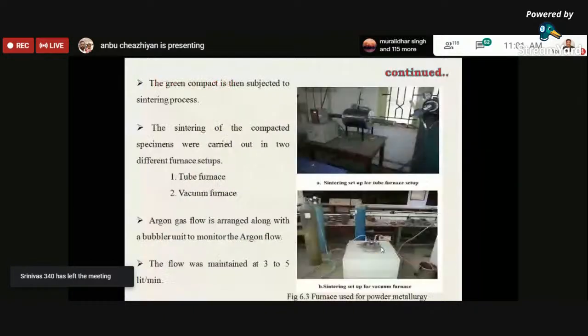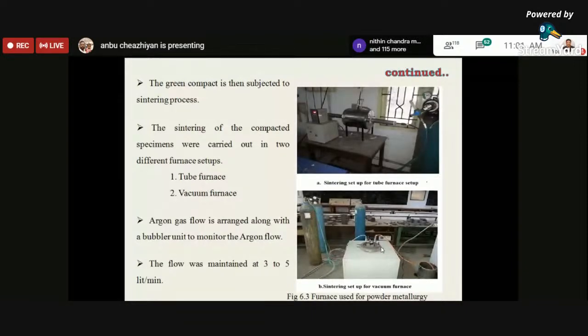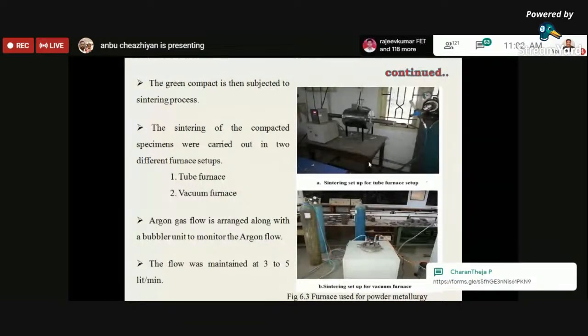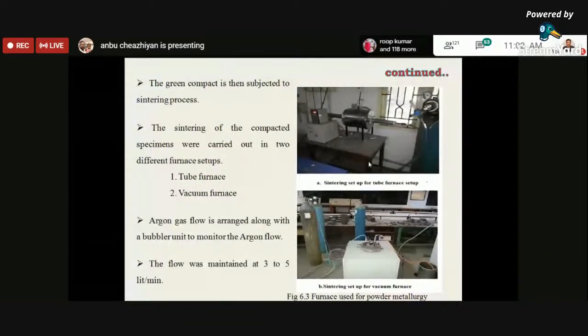And here we have done experiments in two furnaces. One is a tube furnace and another is a vacuum furnace. These are available in Anna University. After compaction, the materials are subjected to sintering. The sintering has been carried out in both furnaces, the tube furnace and the vacuum furnace, to prevent oxidation. As I told earlier, magnesium is prone to oxidation at open temperature, so we need a closed environment.